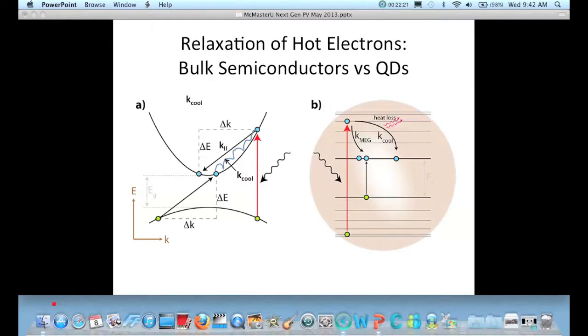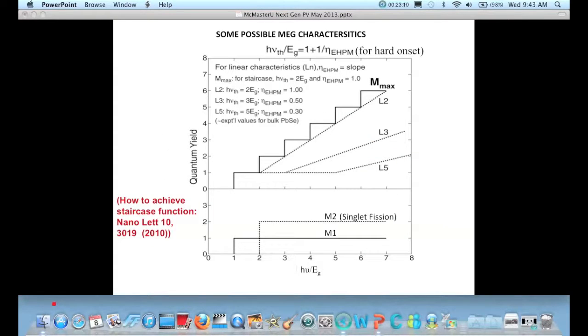So this just shows the competition of the relaxation of these high energy or hot carriers. In this case, I'm just focused on the electron. In the bulk, you excite, but it can undergo this cooling, and it's very fast. It's about a picosecond or less to go from the high energy state to the bottom of the conduction band, and you emit one phonon at a time. And the impact ionization is this process here, which cannot compete with the cooling unless you have a very high energy photon. But in a quantum dot, you can slow down the cooling because of these discrete states, and therefore the rate of multiple exciton generation, which we call MEG, can be competitive with the cooling rate, and indeed it does.